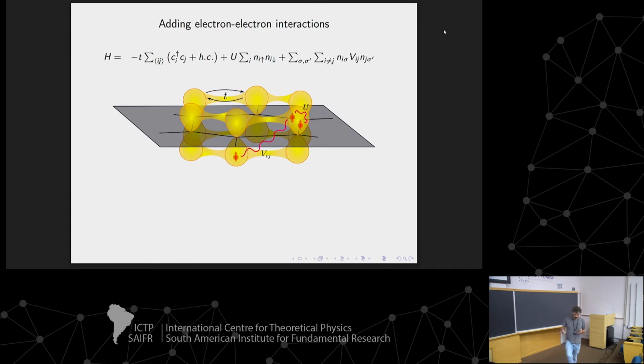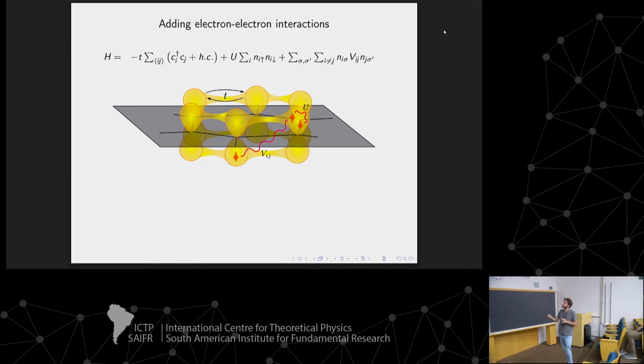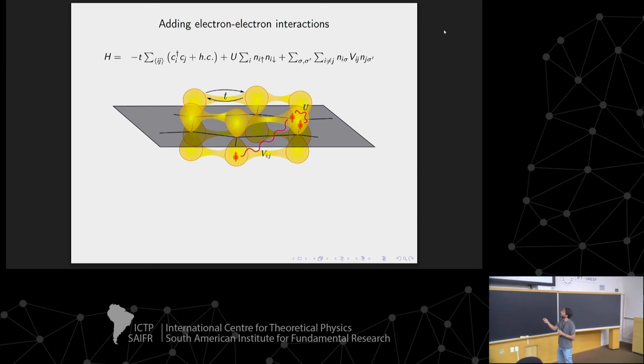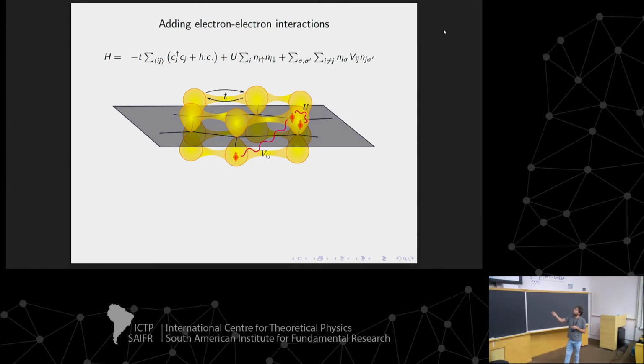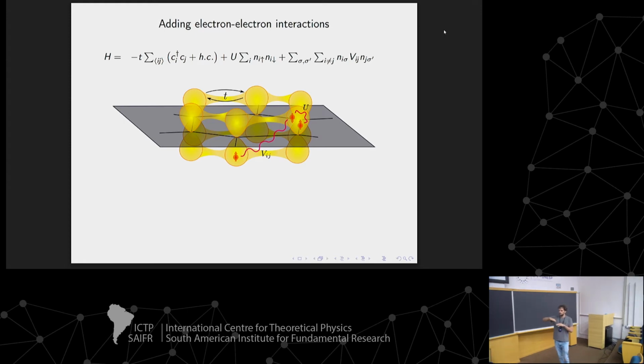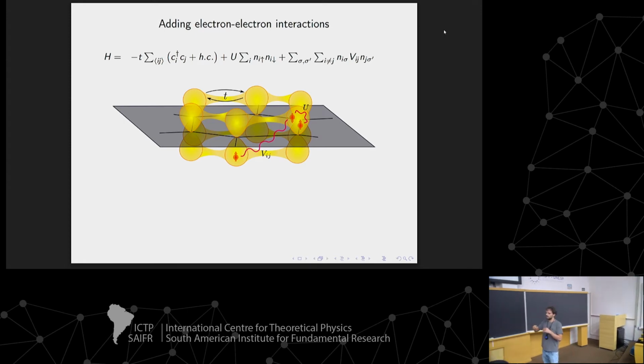I can say, let's do the simplest thing. We can add, for instance, a Hubbard term that essentially penalizes our system whenever two electrons are sitting on the same pz orbital, if you have a double occupancy. And you can even add another term that is a Coulombic term, a long-range interaction term, resulting from having electrons in close vicinity in space, okay? So we expect that this term is there in the case of graphene because despite graphene being a semi-metal, the long-range Coulomb interactions are not going to be that strongly screened because we have nothing below and nothing above that sheet of graphene.